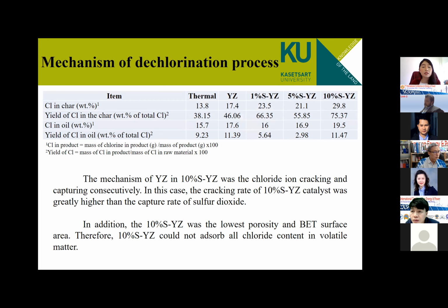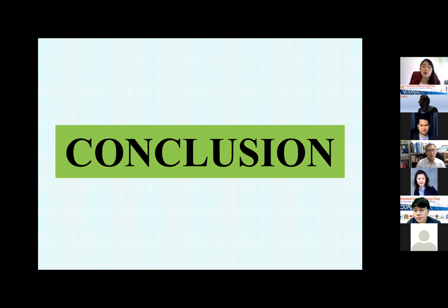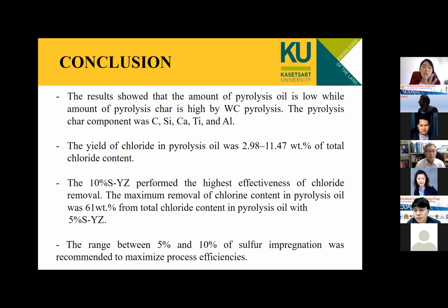In this one, the mechanism of YZ in 10%S-YZ was the chloride ion cracking and capturing consecutively. In this case, the cracking rate of the 10% sulfur catalyst was much higher than the capture rate of the sulfur dioxide. In addition, the 10% sulfur rate had lower porosity and BET surface area. Therefore, 10% sulfur could not absorb all the chloride content in the volatile matter.